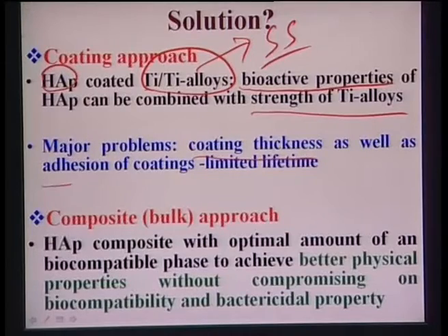But the major problems are the coating thickness as well as the adhesion of the coatings. Coating thickness means if the coating is not very thick, then the coating does not have a longer lifetime, and if the coating is very thick, then the coating can be ruptured or delaminated from the substrate. So both aspects create a limited lifetime for these hydroxyapatite coatings.